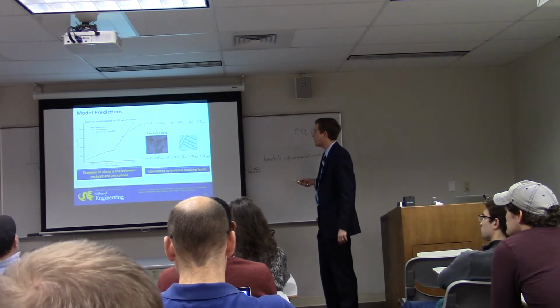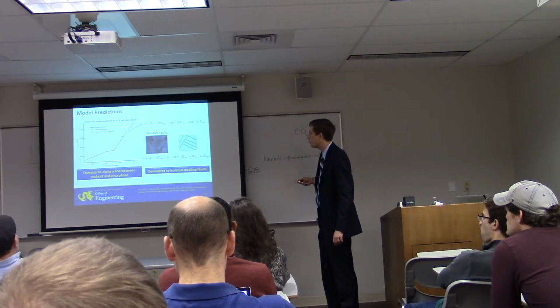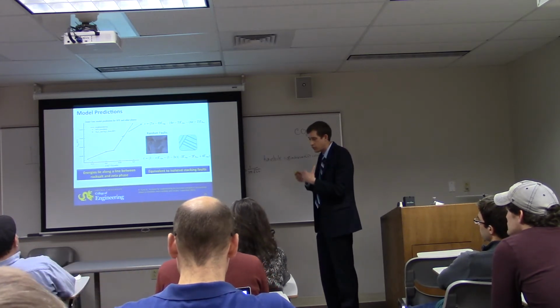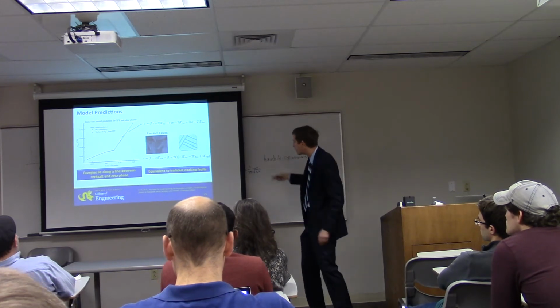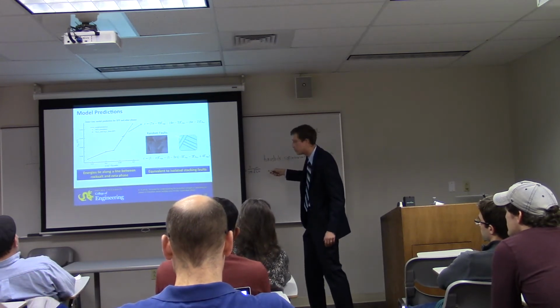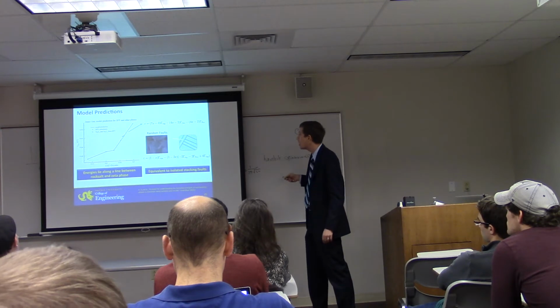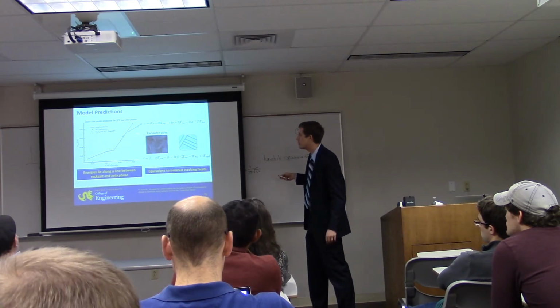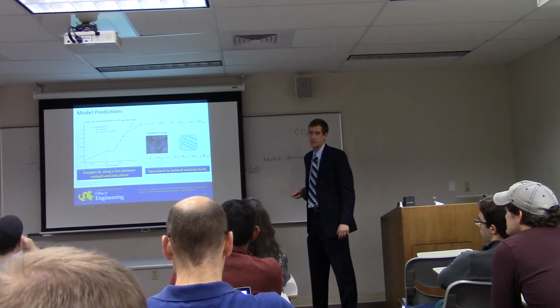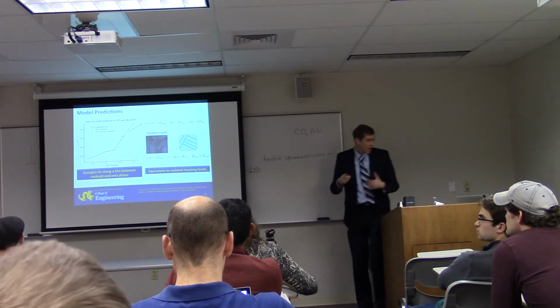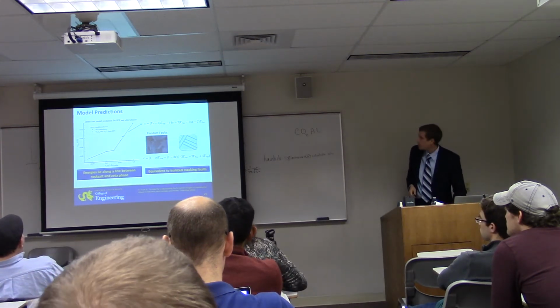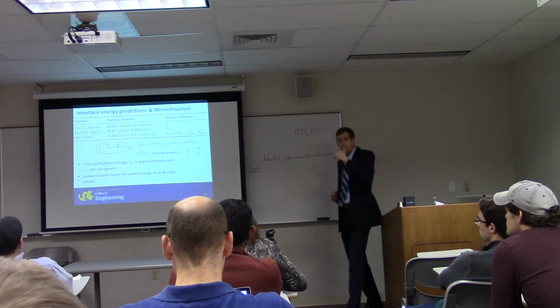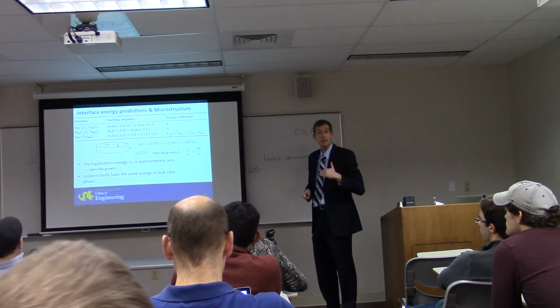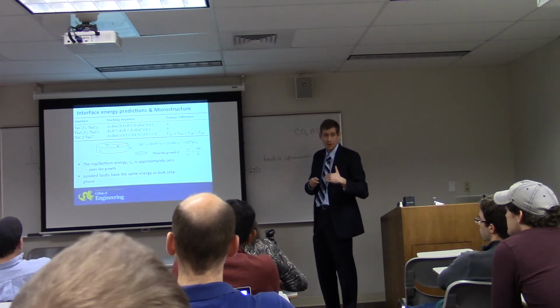And with some algebra, you can show that these two equations are identical. In other words, anything that sits along here, within a non-interacting regime, if you exclude these local interactions as energy penalties, isolated stacking faults are equally favorable as the zeta phase. Right? And I think that's a very powerful message. That was actually the second thing I said, and the conclusions that I started with.